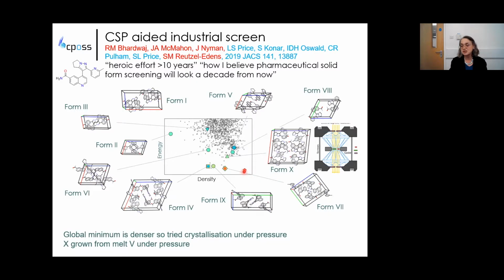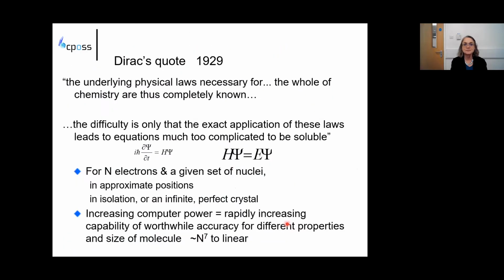And so they commissioned the group in Edinburgh to try crystallizing under pressure. And that's what found Form X. But we still have that time bomb of the most stable crystal structure hasn't been found. And we tried to rationalize in this paper why we hoped that it could never be found. So hopefully that's given you an impression of the amount of work that goes into experimental screening and polymorphism.